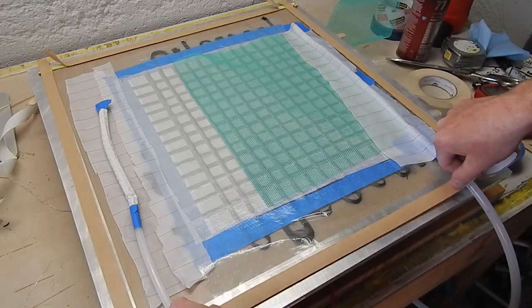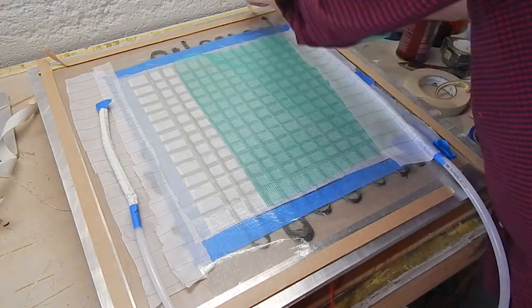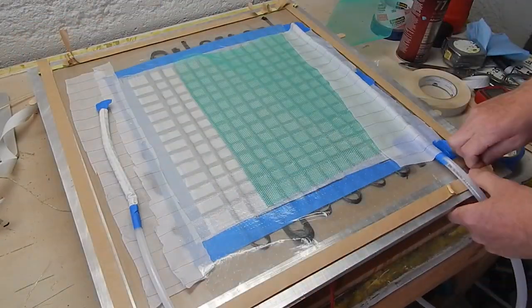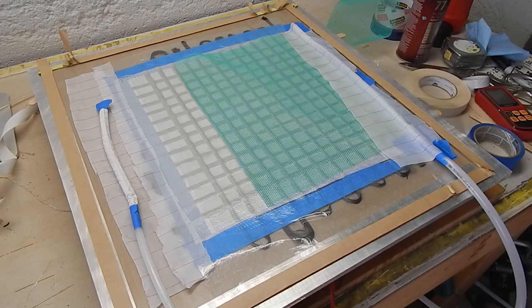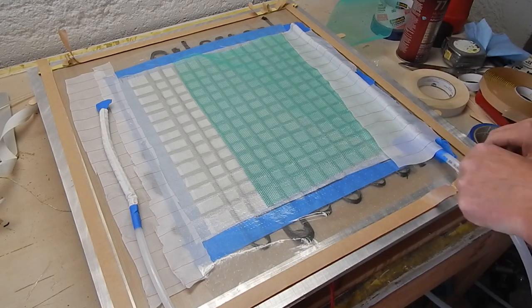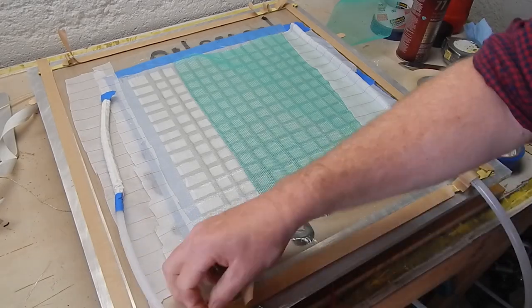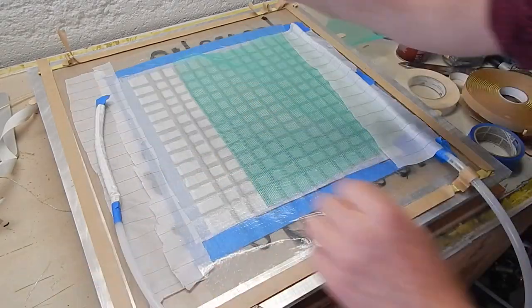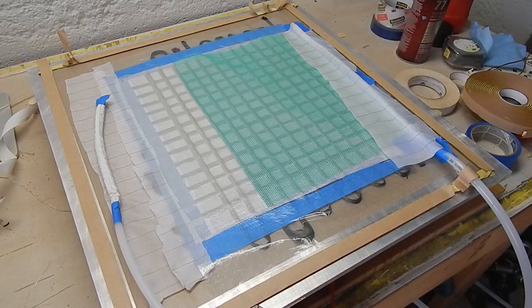I'm going to put down the sealant tape around everything. Sometimes it's nice to put the sealant tape down before you do the layup, just to make sure there's no fibers stuck underneath. I'm going to put each hose up in a little pleat and pre-form the pleats.